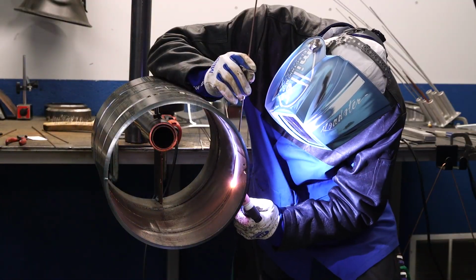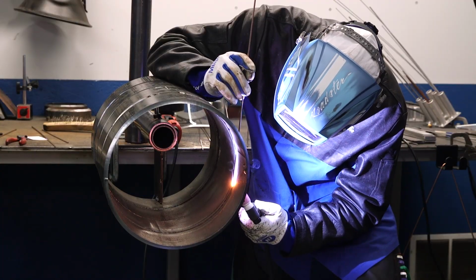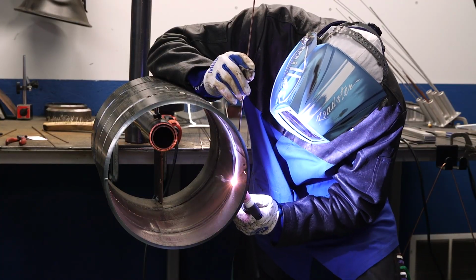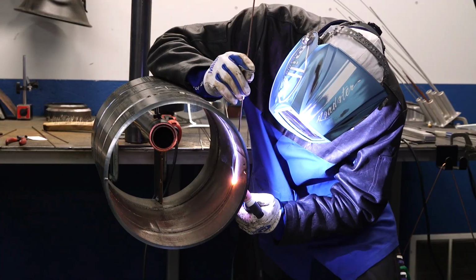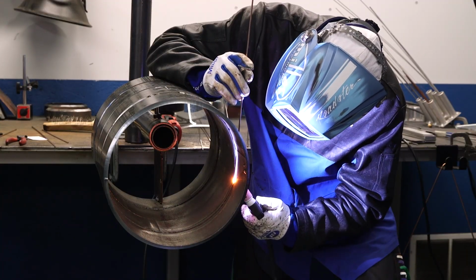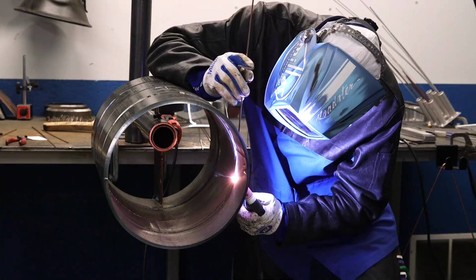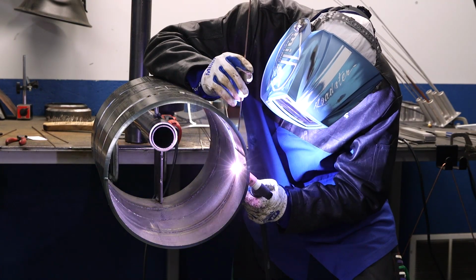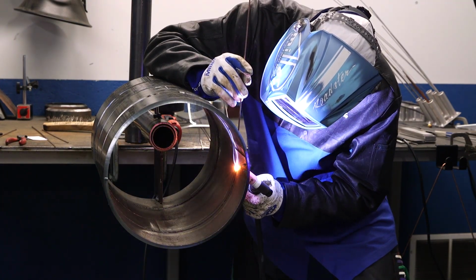Yeah, and having that large molten puddle, gravity will affect you more, whereas having that smaller puddle where it freezes by the time you travel to the other side, gravity has less time and less of a chance of giving you that suck back or undercut. And that's something to really keep an eye on the bottom. On the bottom you're worried about suck back and underfill concavity. On the top you have gravity fighting the opposite way. That wants to suck your puddle down and give you excessive penetration. So keeping gravity in mind, using your heat to your advantage, adjusting accordingly is something you have to pay attention to.